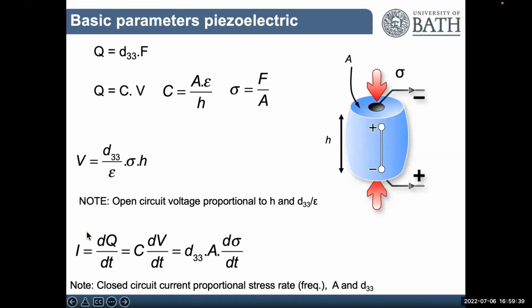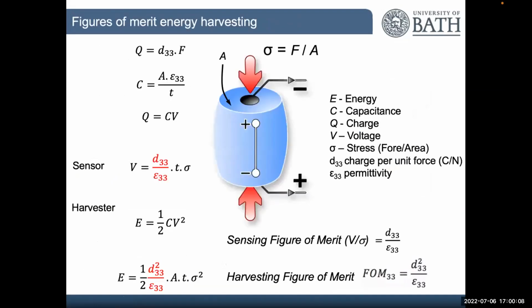The current, on the other hand, is different. The current is proportional to the area. And that's because, remember, it's the surface charge, the screening charge that you're collecting. So you get different effects. Voltage is driven by height and also D33 and permittivity. Current is related to area and just D33. So there's a variety of balances, and we'll see that in a moment. So for a good sensor or for a high voltage, this is what we want. We want a high D33 divided by permittivity in terms of material properties.